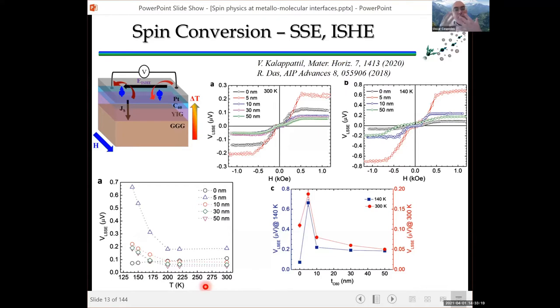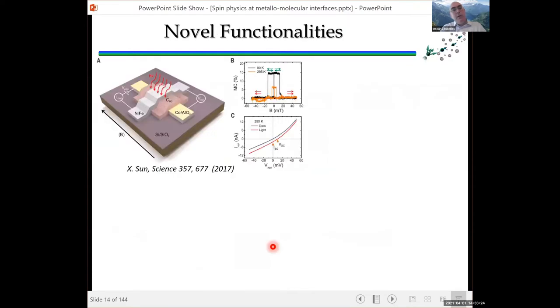Of course, there are people who also study new functionalities. I mentioned before spin photovoltaics in the group of Wessel, where the C60 acts as a solar cell, very low efficiency, of course, because it's not a proper solar cell, but still a photovoltaic effect, where the response that you have depends on the relative alignment of the two magnetic electrodes used there. And obviously, because you have a current that is dependent on the photoexcitation, you can have huge magnetoconductance ratios, because you can go from having no photocurrent to a small photocurrent. So the ratio is actually enormous.